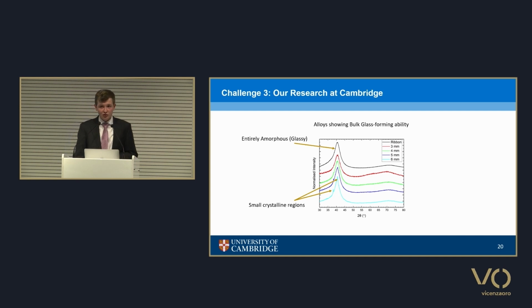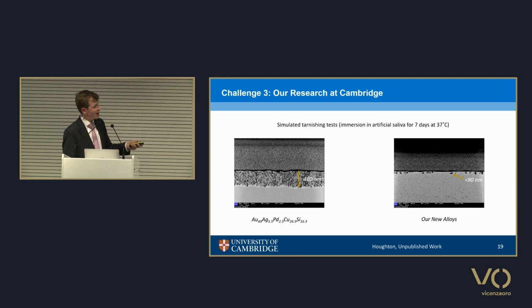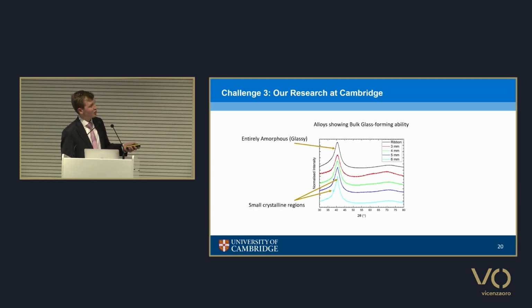Obviously, that's only one half of the story. We've got to improve the glass formability as well. So these are X-ray diffraction measurements. These are the thin cast ribbons that we start at, and these are about 100 microns, 100 micrometers, in thickness. And then we try to develop even thicker castings. As you will see in the samples at 5 and 6 millimeters, we start to see these crystalline peaks, and that's indicative of some crystallization occurring. We think they were to do with palladium silicides, and so there is room for further optimization. And so hopefully we'll be able to pair this with this, but for very thick sections.